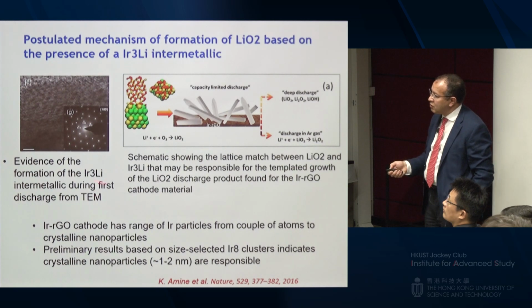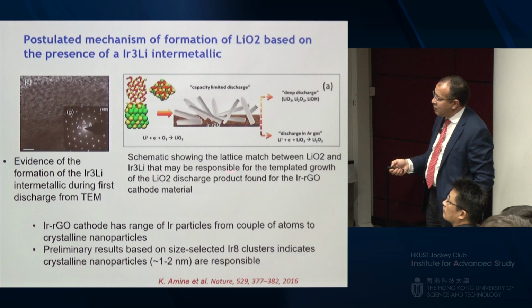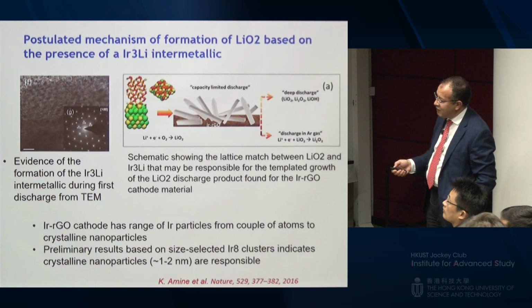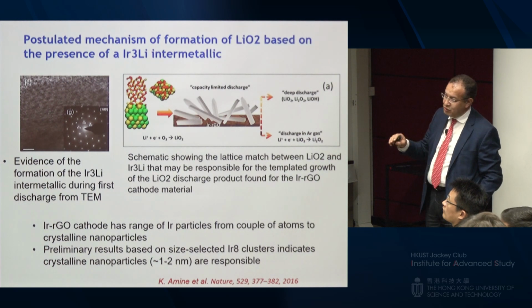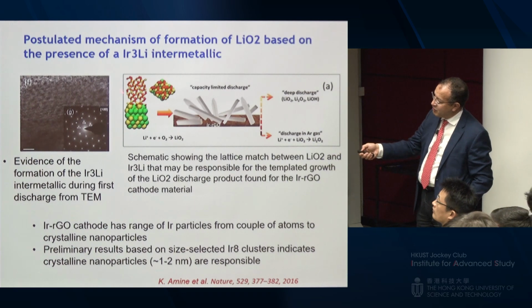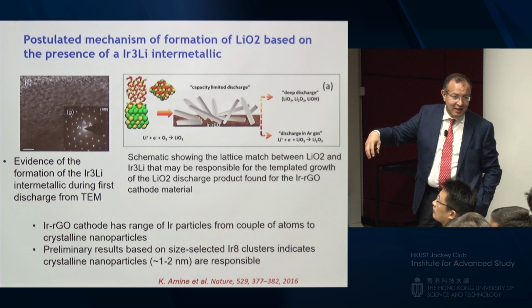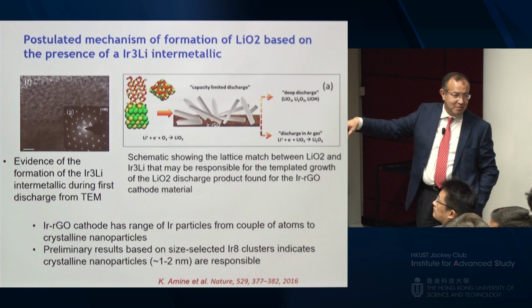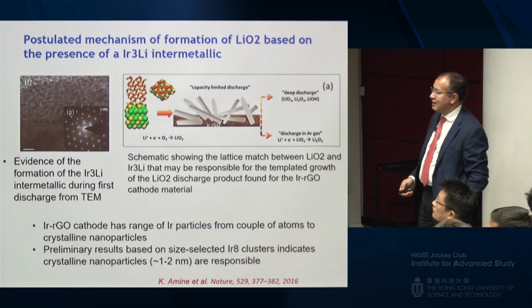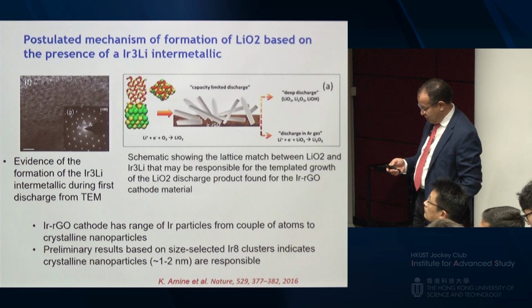But if you look at the structure of this catalyst, and look at the lithium superoxide structure, they have a lattice match between the two. So basically, the superoxide is capped on the top of the catalyst. And that's the reason why we've seen most of them, because the catalyst is highly dispersed, and the superoxide grows on the top of this catalyst. That's mainly the reason why it's stabilized.